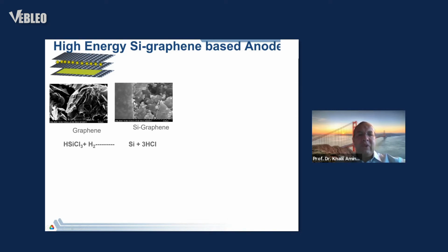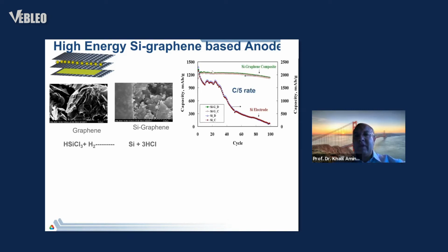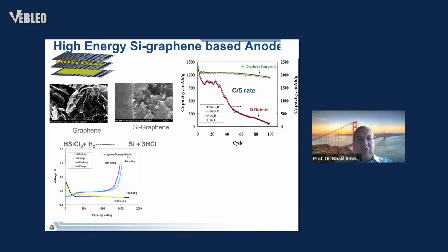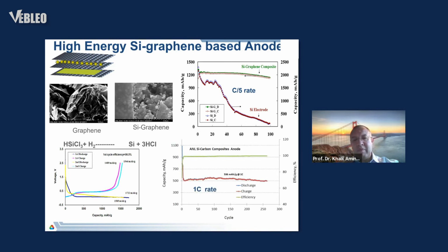The morphology of the silicon is spherical, but very small. It's less than 150 nanometers, so it takes a long time to crack to start with. And if there is cracking, this sheet of graphene will collapse on the cracked material and keep conductivity. And you can see clearly the impact here is very significant. We're also seeing some improvement in efficiency, but we still have a very large irreversible loss that needs to be addressed. Now, if you reduce the silicon amount, you can get lower capacity, but still higher than graphite, but you can operate at high rate and get very significant cycle life out of this system.